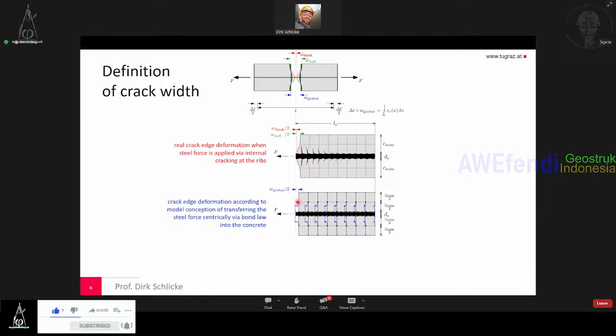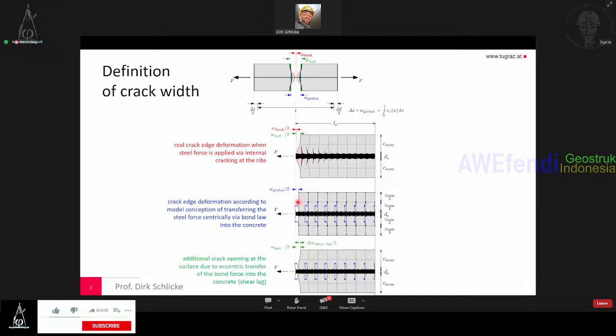The shear lag, which refers to shear deformation of a solid material, can then of course occur if you apply these bond springs at the contact area between reinforcement bar and the concrete cover. Then you get some shear deformation as shown here, which can of course increase the surface crack width. The real mechanism can only be obtained with 3D FEM simulations with concrete fracture, actually. And the other simplifications refer then to analytical models based on bond law.